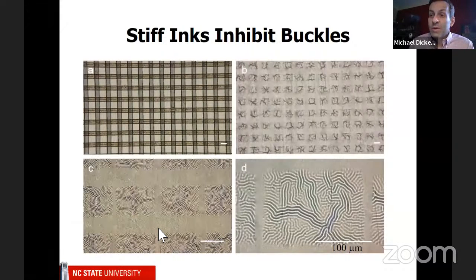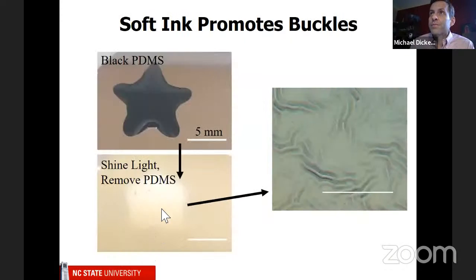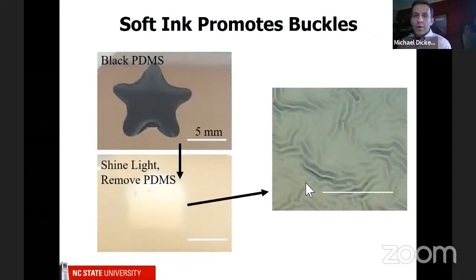And then we did the experiment with the soft ink. This is silicone, which is soft, and we made it black by mixing it with some carbon particles. And you can see that when we shine the light, we used a different light source here. Actually, we used an LED. Nothing happens here, and then something is happening here. You can see it looks a little bit different once we remove the silicone. And if you look underneath it, sure enough, there are some wrinkles. They're not quite as pronounced, but they're there.